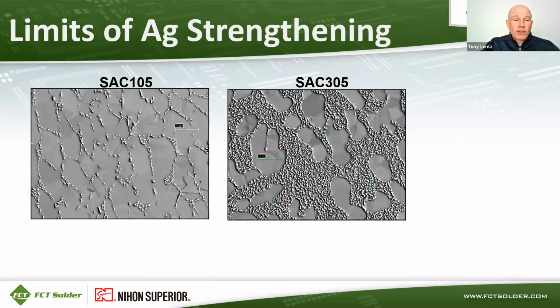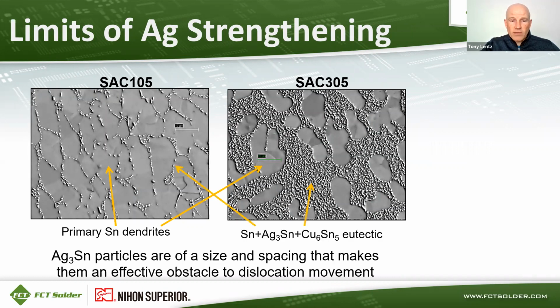Here's some cross-sectional pictures of SAC 105 and SAC 305. You can see primary tin dendrites, as well as a mixture of Ag3Sn and Cu6Sn5 eutectic particles within the solder matrix. And those particles are of a size and spacing that make them an obstacle to dislocation movement. And what that means is that those particles help to strengthen the solder, and they help to resist shear or cracking of the solder joints.